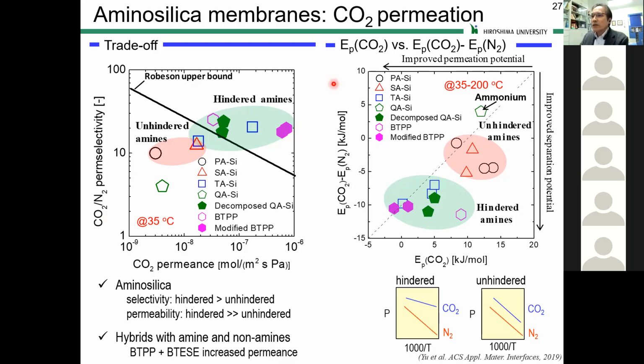So this was analyzed based on activation energies. The activation energy of CO2 minus nitrogen is now plotted against the CO2 activation energy over here. For unhindered amine, it is very close to zero. It indicates that for unhindered amine types, primary amine and secondary amine, CO2 and nitrogen are activated in a similar way. On the other hand, for hindered amine, activation energy CO2 minus nitrogen is now becoming negative, which indicates that the activation energy of CO2 is smaller than nitrogen. So it is important to control the diffusivity and the affinity with the membranes.